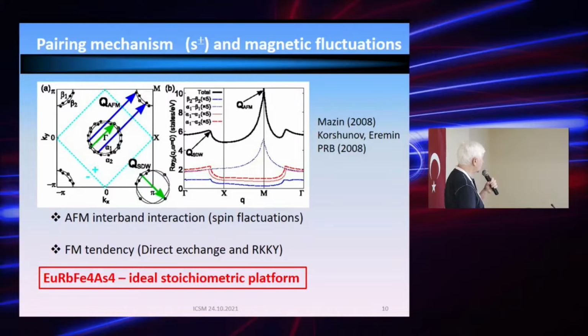spectrum of excitation, there should be a peak, and this peak also was found in neutron scattering measurements. So most theorists and experimentalists currently consider that this picture is behind the magnetic pairing. So pairing happens due to magnetic fluctuations in the two-band electronic system of iron arsenide orbitals.